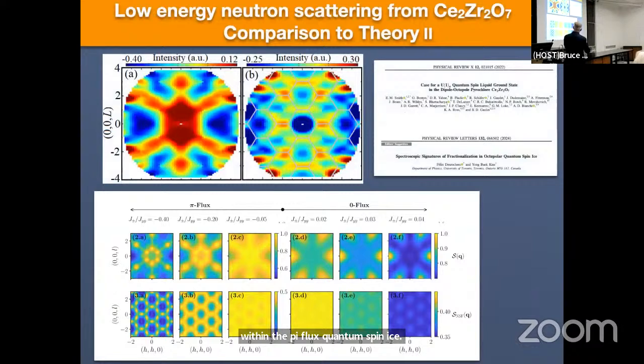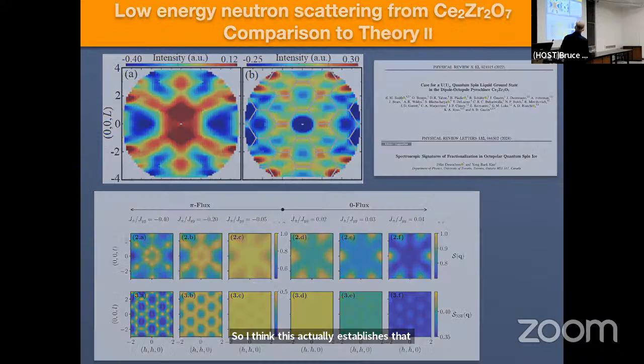So this is the same calculation that I showed before. This is a calculation of the non-spin flip polarized diffraction that they would expect for the same set of parameters. And for the example where we had the good agreement with our unpolarized structure factor, we also have good agreement for this diffuse scattering along zone boundaries of the FCC lattice in the non-spin flip channel. So I think this by itself is very compelling evidence that what we're seeing in cerium zirconate is a pi flux quantum spin ice, okay, at 60 millikelvin. So I think this actually establishes it very well. There's still a whole bunch of open questions, but that part of it is established.